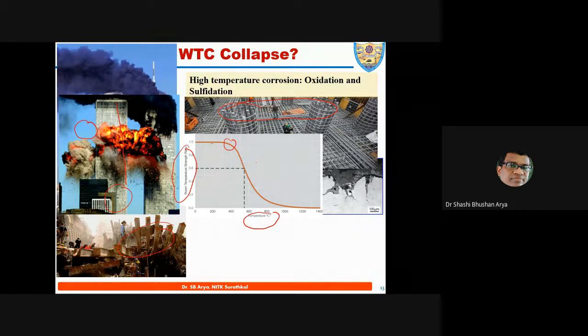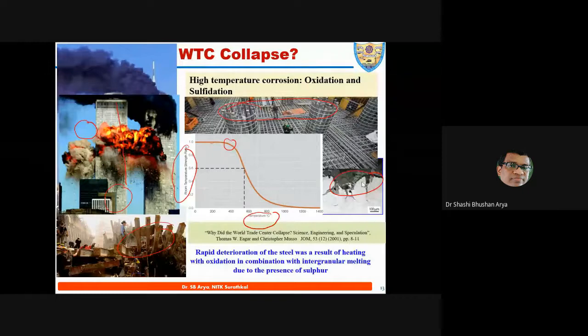When the temperature increases beyond 400, the weakening will start. And the inside temperature was quite higher, and the steel inside this concrete structure got softened. When it got soft, obviously the load bearing capacity, you know in the composite structure, who will take care? Reinforcement. When the reinforcement has a problem, the damage will be much more actually, and that's why it happened. This World Trade Center typically failed because of, one, the high temperature, and second, the sulfur and iron reacted and reached the grain boundary and formed iron sulfide. They assisted more failure actually. This is a well documented study published in the Journal of Materials by one of the researchers at the Massachusetts Institute, MIT, and they published 2-3 volumes continuously.